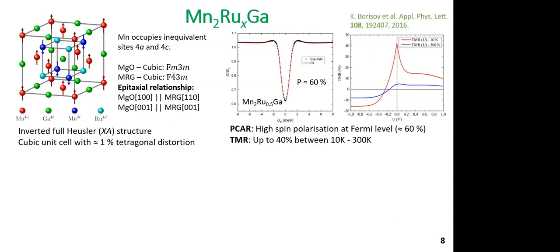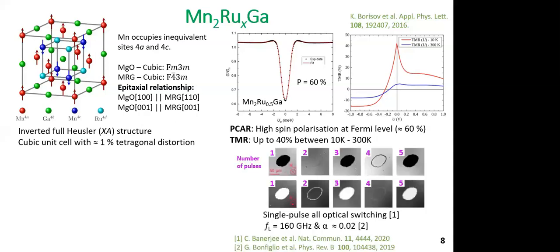TMR was found to be up to 40%, measured between 10 Kelvin and 300 Kelvin, for MRG integrated into MgO-based perpendicular magnetic tunnel junctions. Time-resolved MOKE measurements so far demonstrated a maximum zero applied field resonance frequency of about 160 gigahertz, and the intrinsic Gilbert damping constant alpha was found to be 0.02. So this is fairly low, as we would have expected.